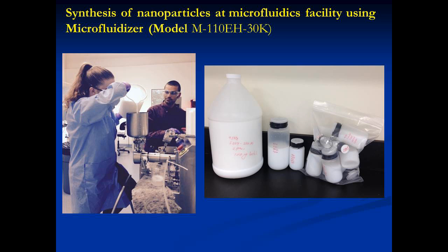You can see here the Microfluidics people, particularly Steve and Kristen, at work. We are making nanoparticles in liters using a different model, the M-110EH-30K. Interestingly, the size of the nanoparticles we made in the LM10 and the size of those made in the M-110EH were more or less similar, if not identical. So whatever we were looking for, we got the same size nanoparticles but in a different amount of fluid.